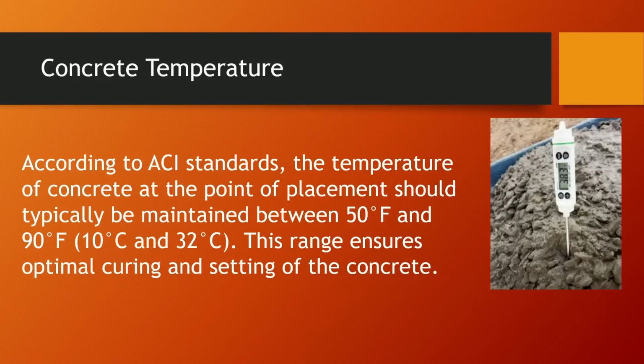Okay, concrete temperature. According to ACI standards, the temperature of concrete at the point of placement should typically be maintained between 50 and 90 degrees F. This range ensures optimal curing and setting of the concrete. So when your third party gets the mud from point of placement, or however your specification is requiring it, typically it's point of placement, they're usually going to put it into a bucket, or they're going to put it into a little wheelbarrow. They should be dumping a thermometer in right away to make sure the temperature meets ACI standards.